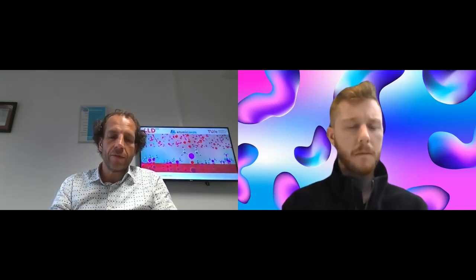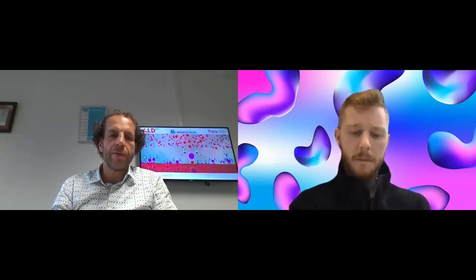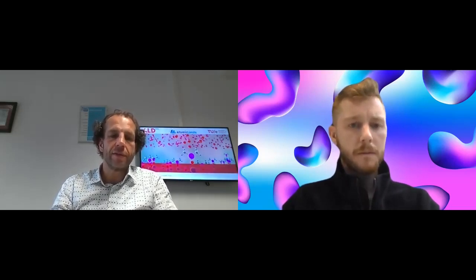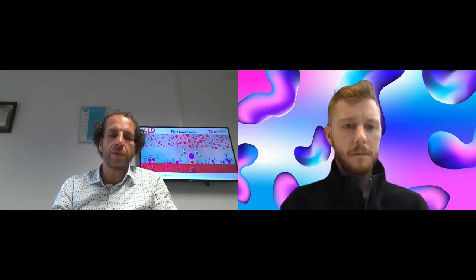So that is the classic case of aluminum oxide, and I think this holds for more oxides, that the surface chemistry is somewhat different because you have combustion of the surface ligands, but maybe the end result, or how the surface is terminated, is the same. Now, for nitrides and for other materials, it's sometimes somewhat different, I would say. But then it's also somewhat harder to compare. For example, some nitrides are difficult to make with thermal ALD, like silicon nitride. So then you cannot really compare the surface chemistry. So it very much depends on the material that you deposit, of course, but the bottom line is that it's sometimes not that different.